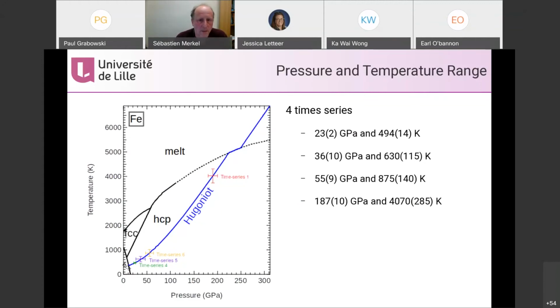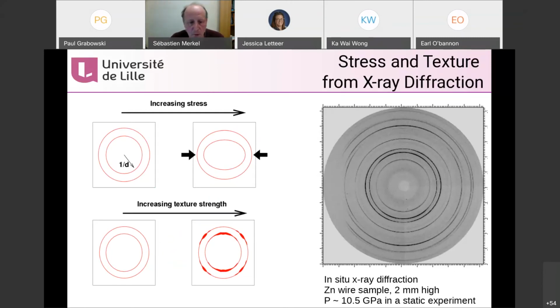The idea is this is a type of measurement we do in static experiments to look at stress and textures in polycrystals. These are measurements in a large volume press on zinc. You collect 2D X-ray diffraction with a specific geometry where you can actually see the effect of stress. As you compress the material, if you put stress, the Debye rings will be distorted and will become like ellipses. And as your grains rotate, you'll develop textures, lattice preferred orientation, and that will show up as variations of diffraction intensity. It's not easy to see on such a figure, but if you look at the integration as a function of azimuthal angle, delta or eta angle depending on convention, then it's easier to see.